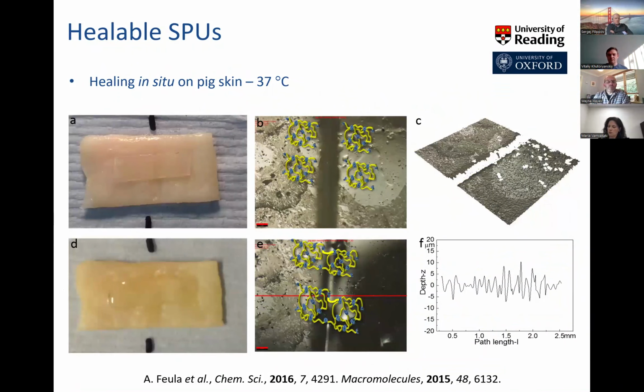Now, these materials were also really nice adhesives, and what we've shown here is the polymer in photograph A. You can see the polymer, a rectangle, and it's actually adhered onto a pigskin. And in the middle there, indicated by the black lines, there's a very, very faint line, which is where we've cut our polymer with a scalpel. Then we've exposed that to 37 degrees C, and you can see that the pork skin cooked slightly.